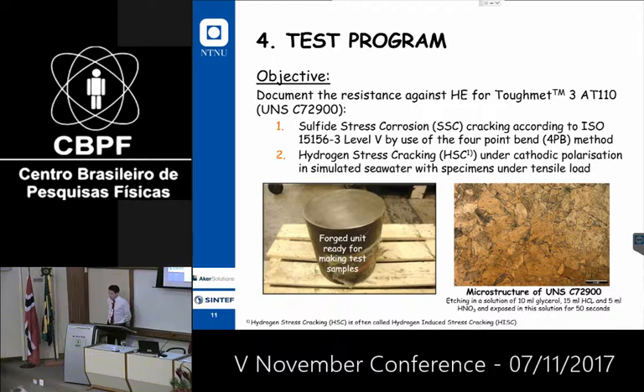So what we did here, we took a forged unit and harvested samples for sulfide stress corrosion exposures according to ISO 15156-3 Level V by the 4-point bend method, and in addition we did hydrogen stress cracking under cathodic polarization in simulated seawater with specimen under tensile load.